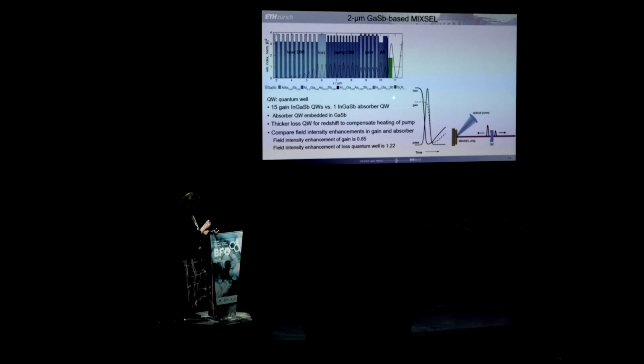It is because in the semiconductor you have so-called dynamic gain saturation, which you don't have in solid-state lasers. So from pulse to pulse at steady state, you have significant gain saturation. So you have to make sure that the saturable absorber saturates before the gain to open up the net gain window that supports your stable pulse generation. You don't want to make it too resonant, otherwise the whole system becomes very tricky to work. And you also want a rather fast saturable absorber, which we could get with this indium gallium antimonide saturable absorber. And there's a whole bunch of really interesting physics only on this absorber, which we have been able to characterize. Next slide.